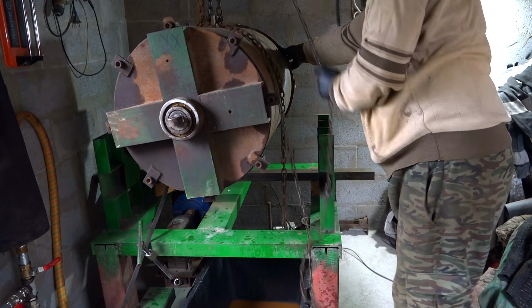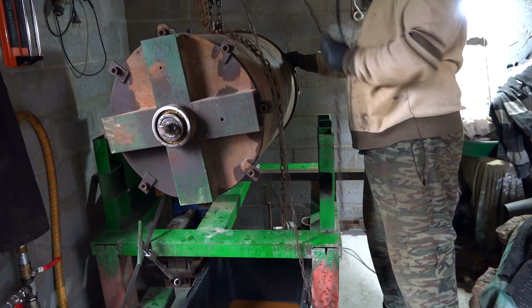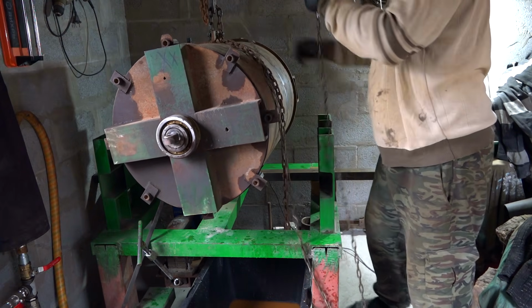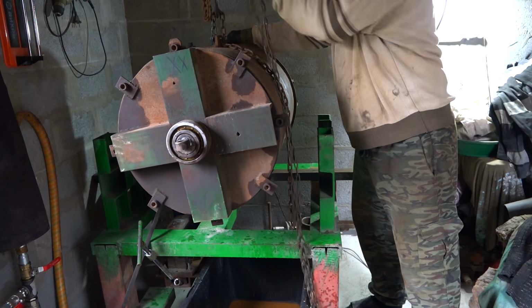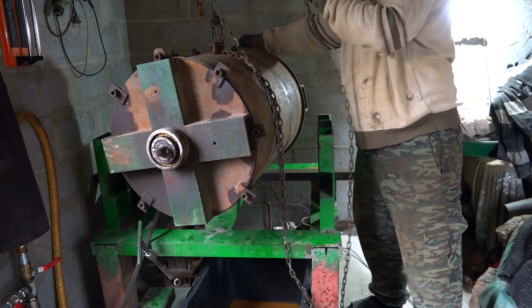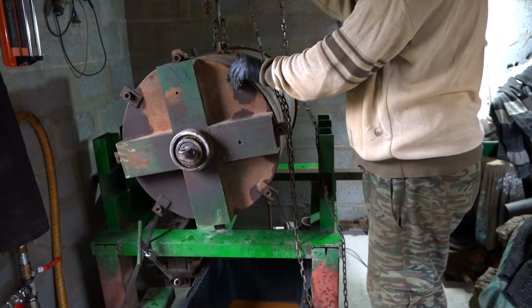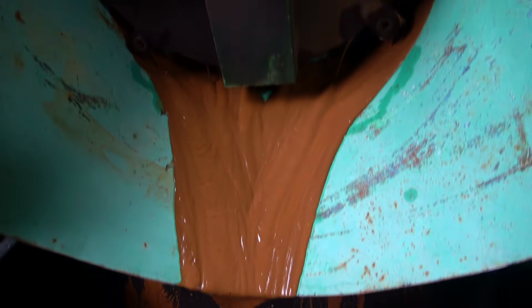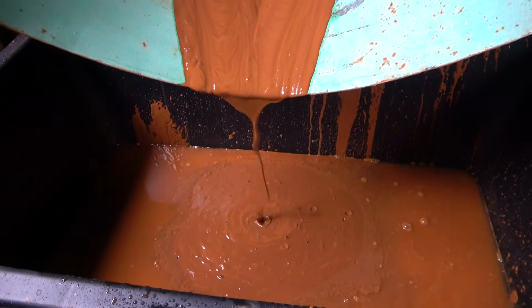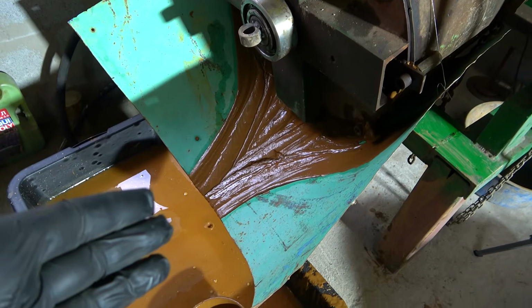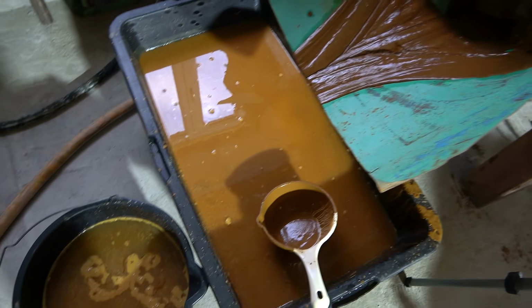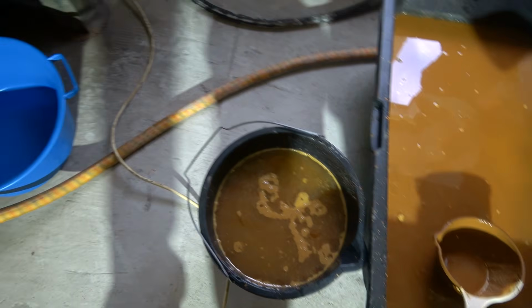And if you unload through the hatch, then there is a high probability that large gold particles will remain in the drum between the rods and at the very bottom. And it's very inconvenient to flush from below. There will be a lot of dirt around. In my case, the hatch is designed only for loading material. I poured half of the volume into a basin, about 100 kilograms.